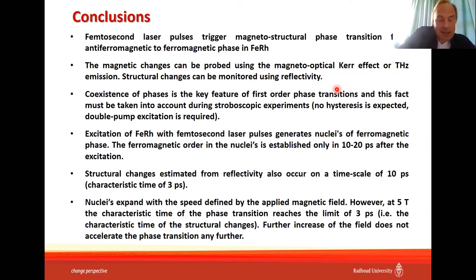People came with this hypothesis already earlier doing X-ray measurements, and now we confirm this with terahertz and explain where the terahertz emission comes from. So structural changes estimated from the reflectivity also occur on the time scale of 10 picoseconds, meaning a characteristic time of roughly 3 picoseconds. And as I said, this time scale can vary from sample to sample because it's defined by the thickness of the sample divided by the speed of sound in the material. And nuclei expand with a speed defined by the applied magnetic field. However, already at 5 Tesla, the characteristic time of the phase transition reaches the limit of 3 picoseconds, the characteristic time of structural changes. And a further increase of the field does not accelerate the phase transition any further.